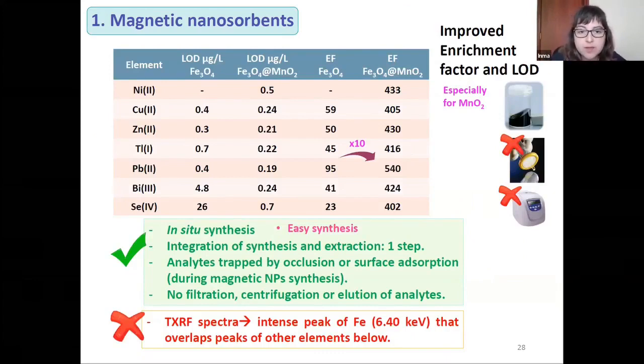To sum up, we can see that this synthesis is very easy and it produces an integration of steps, having the synthesis and extraction of analytes in only one step. So the analytes can be trapped by occlusion during the coprecipitation of the magnetic nanoparticles, and other elements can be trapped by surface adsorption to these nanoparticles. Additionally, no filtration and centrifugation is required because of the easy magnetic separation, and also elution is avoided because the TXRF analysis allows the analysis of this suspension of the magnetic nanoparticles.